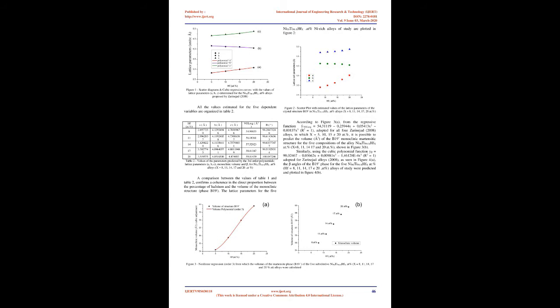Prediction of the B19' phase of Ni50Ti50-xHfx at% alloys. Based on the graphs by Zarinejad, 2008, 1, whose measurements were obtained by XRD refinement method, it was possible to calculate, through numerical proportions, the equivalence of the lattice parameters a, b, c, volume of the monoclinic structure B19' and axial angle β, as shown in Table 1.